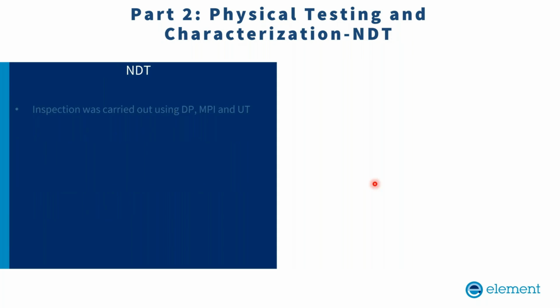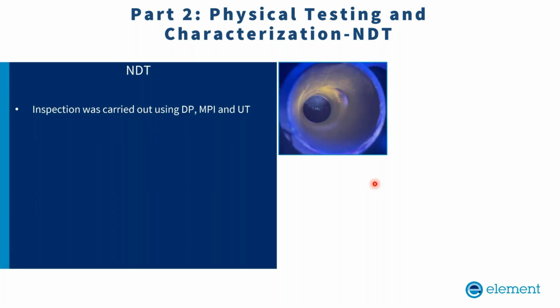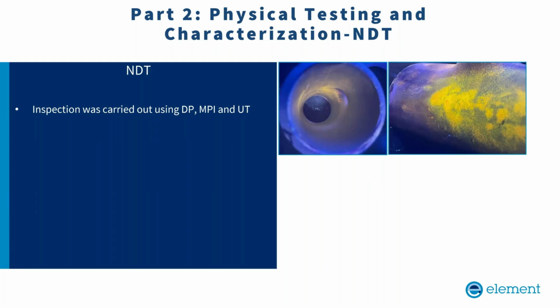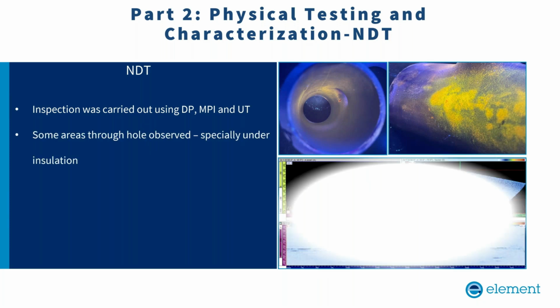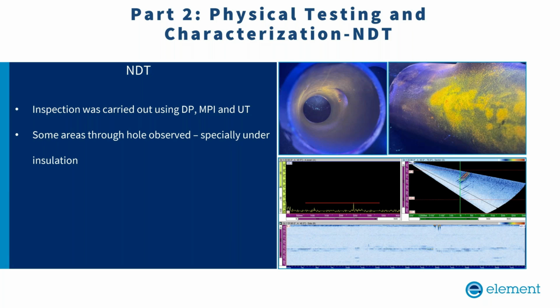A thorough NDT examination was carried out using MPI, dye penetrant, and ultrasonic testing. In some areas we have seen through holes, as I mentioned previously. We have done fluorescent magnetic inspection, which shows severe presence of corrosion at the surface. We also saw during UT a through thickness crack inside the material. So the initial NDT investigation suggested that surface corrosion is the main corrosion problem of this asset, and also there was some through thickness crack present in some locations.